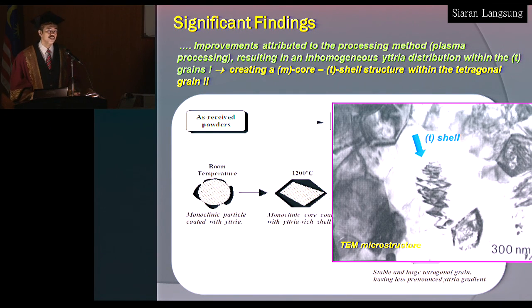Now, this effect we don't find in co-precipitated powder, because in co-precipitated powder, the yttrium oxide has been distributed homogeneously within the structure. So therefore, it stabilizes the structure, and the yttria distribution from the shell to the middle is almost constant.